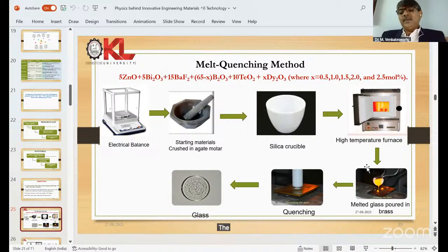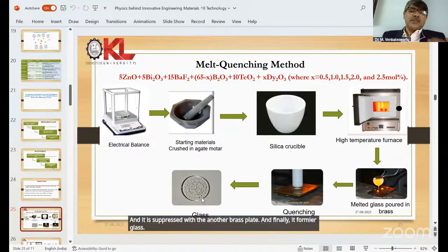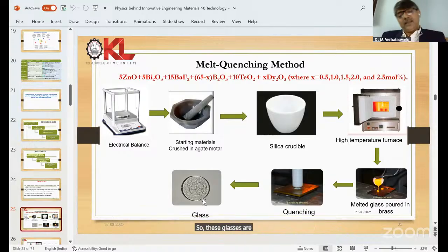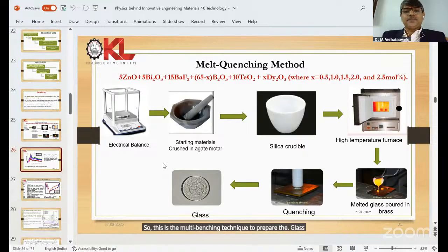The melted liquid is poured onto the pre-heated brass plate, and it is pressed with another brass plate, and finally it forms a glass. These glasses are placed for annealing at 350 degrees Celsius for 1 day, to reduce the thermal strains in the material. So this is the melt quenching technique to prepare the glass materials.